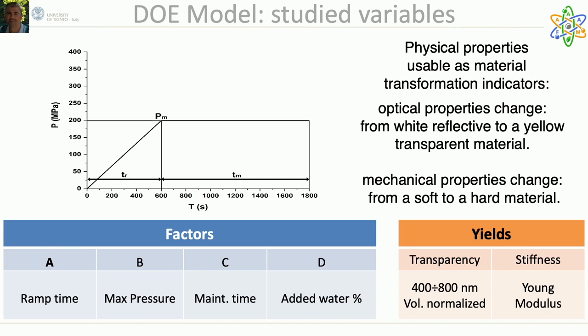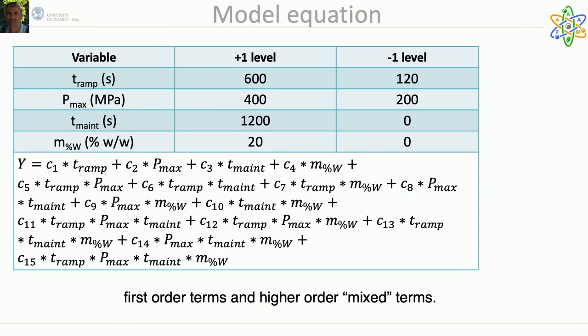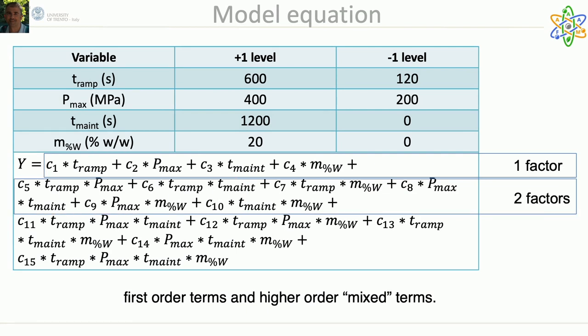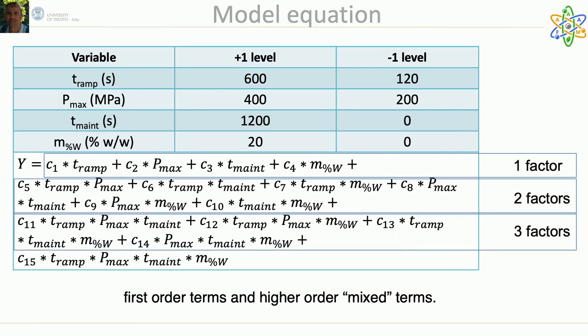Factors studied in the model were the maximum pressure applied to the mold, the ramp time, that is the time to reach the maximum applied pressure, the time the mold is kept under pressure, and the percentage of the water added. These four factors have been then combined to build up an equation containing the weighted contribution of the proportional terms and all the combination of the mixed terms, then evaluated against the experimental values of light absorbance and elastic modulus.